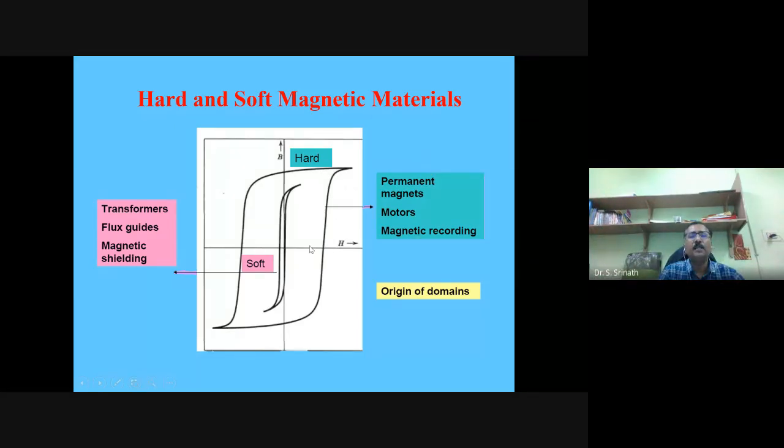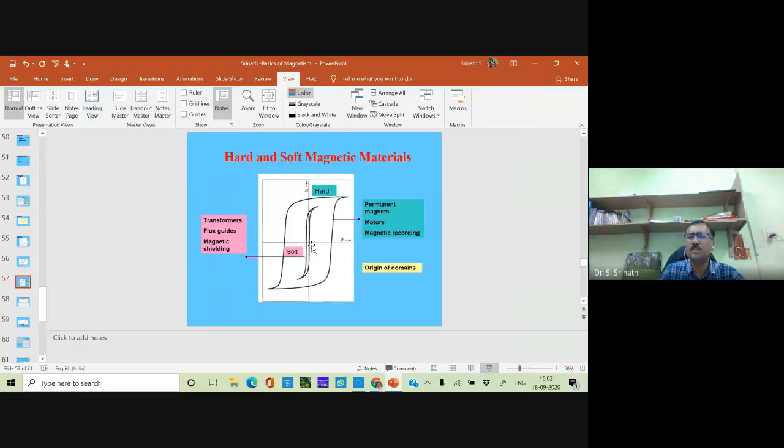If I do that, then most often, only special cases, special materials, of course, there are some effects called training, the history dependent effects, but otherwise, for simple ferromagnets, because we are discussing simple ferromagnets now, the major hysteresis loop is always retraceable. Otherwise, there is no point. You measure today and report some coercive field and remnant magnetization, and I do it tomorrow. If I get some other numbers, then this measurement has no meaning.